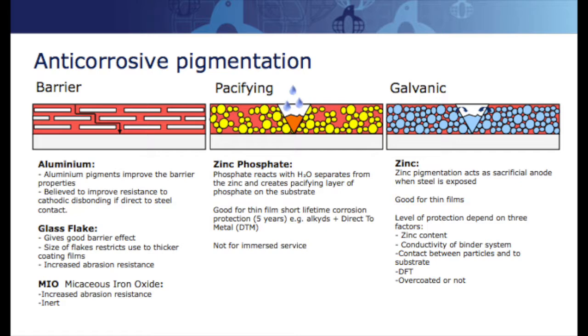Because testing, you normally do in a seawater environment, you put a scribe, you cut through the paint, and then you want that scribe to have as little rust creep as possible after, say, 6 months exposure in a condensation chamber or whatever. Zinc phosphate will help to protect that scribe. It's only 6 months. That's a short period of time. So the zinc phosphate does a great job of making your results in short-term testing look good.